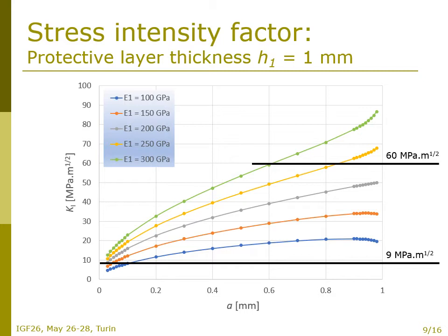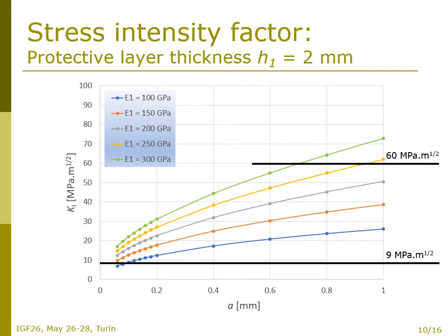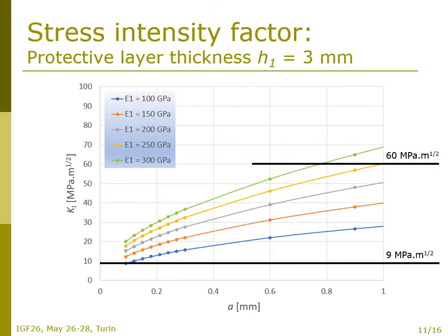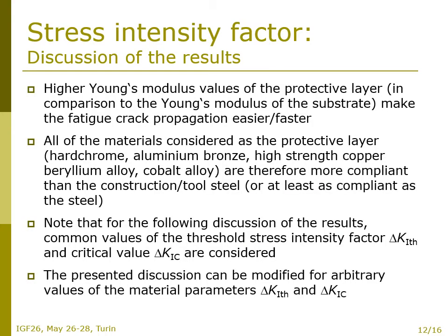These horizontal black lines represent the common values of the threshold stress intensity factor, this 9 megapascals square meter, and its critical value, 60 megapascals square meters. Analogical results were obtained also for the thickness of the cladded layer of 2 millimeters and also 3 millimeters. So you can see how the curves are moving in the same scale. When the results are mutually compared and analyzed, the following discussion can be made.